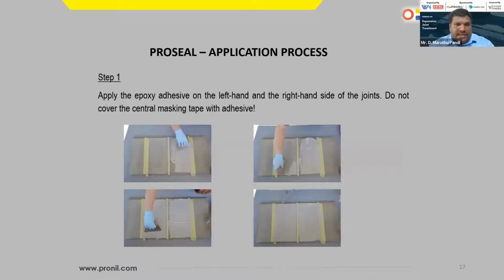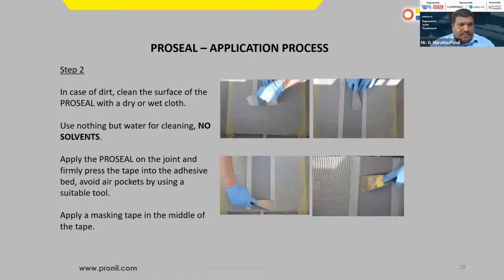And this is the application process. Consider this as a joint, and he will be applying the epoxy adhesive of around 4 mm thickness on both the sides. You can see here. Do not apply adhesive on the center of the tape. Any dirt on the Pro-Seal tape should be completely cleaned with a wet cloth. It should be free from dust and laitance. Do not use any solvent to clean the tape as well as the surface of the concrete.